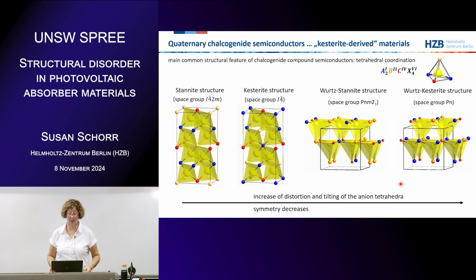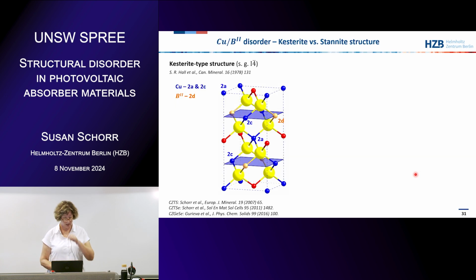Of course, silicon belongs to the same family, so this is the adamantine compound family, and in silicon you also have the tetrahedral coordination of silicon by silicon. But because silicon is cubic, the tetrahedra are not distorted and not tilted. But if you go down in symmetry, then you have an increase of distortion and tilting. It's like in the perovskites. So I showed you the copper zinc disorder, which is existing on these 2 planes here, between the copper site, the 2c site, and the divalent site 2d.